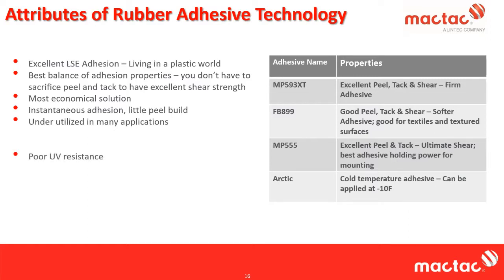However, rubber-based adhesives do have a few drawbacks, which we should talk about. And Steve did mention this with the double bond phenomenon earlier in his discussion about polarity. Rubber-based adhesives do exhibit some poor UV resistance over time. But that isn't to say they can't last outside as long as the adhesive itself is protected by some kind of a film or opaque material. They do have poor heat resistance. Really, once you get upwards of 200 degrees Fahrenheit, that maxes out the performance of most rubber-based adhesives.